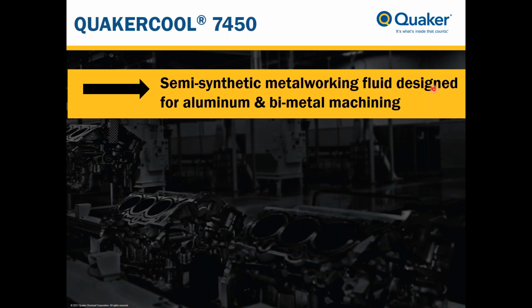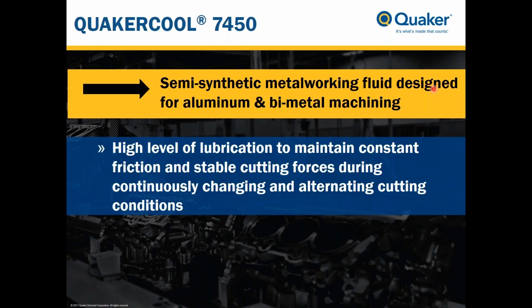I'll just list a little bit of the logic behind the design of this fluid. One, it was designed to provide a high level of lubrication that is necessary to maintain constant friction and, more importantly, stable cutting forces that occur during the continuously changing conditions in a bimetal operation. I mentioned earlier that with the thermal properties, the expansivity of aluminum, the differences and so forth, you can get constantly changing friction and cutting forces. If you can elevate the lubrication properties of your metalworking fluid, you can minimize the impact of these changing forces and changing conditions. And that's a main element of the design of QUAKERCOOL 7450.